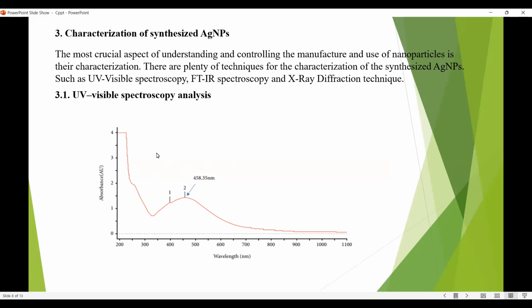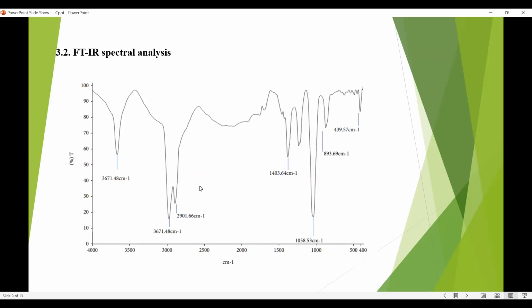Coming to the UV-visible spectroscopic analysis, this is the spectrum we obtained. The UV-visible spectrum in the 200 to 800 nanometer range is used for the prediction of synthesized silver nanoparticles. The surface plasmon resonance of the synthesized silver nanoparticles is indicated by the absorption band at 458.35 nanometer. The UV-visible spectrum is plotted by taking wavelength in nanometer along the x-axis and absorbance in arbitrary units along the y-axis.